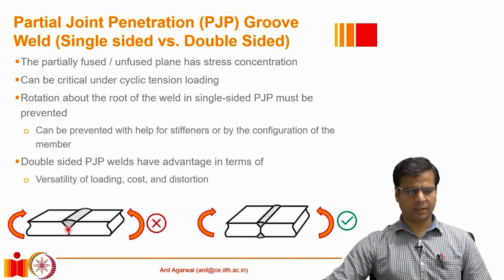So as we have discussed, partial joint penetration groove welds have part of the thickness of the plate that they are joining fused and a part unfused, right? So in this case, you can see these two plates are being joined. This portion of the thickness is fused together, but this portion remains unfused. So whenever we have such a situation where some portion of the thickness is unfused, that interface right there becomes the location where stress concentration can occur under a stress condition. So when these plates are being pulled apart, at that location we can expect some stress concentration, and that's where the crack can start. Especially under cyclic loading conditions, fatigue cracks are quite common, and they are often observed to have started from such locations.